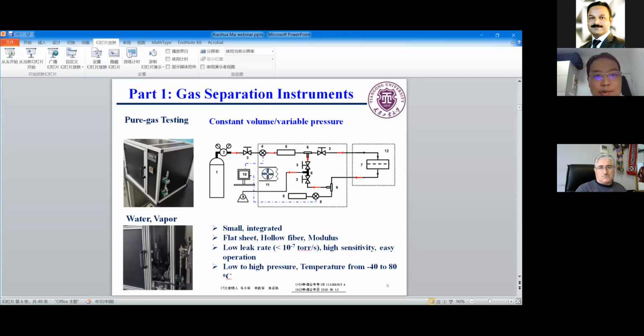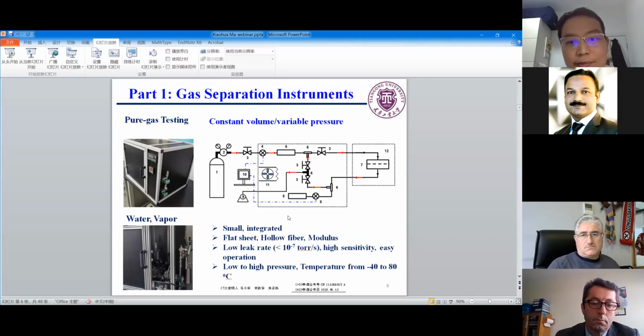Here is the pure gas testing instrument. I made this constant volume variable pressure instrument, based on the constant volume variable pressure method. This instrument is very small and integrated. We can test flat sheet membranes, hollow fiber membranes, and modules. Especially, we can test one single hollow fiber, and also modules. We can test low pressure and high pressure, because I made some changes to this instrument. Recently, we can also test water permeability and some vapor permeability using this instrument.